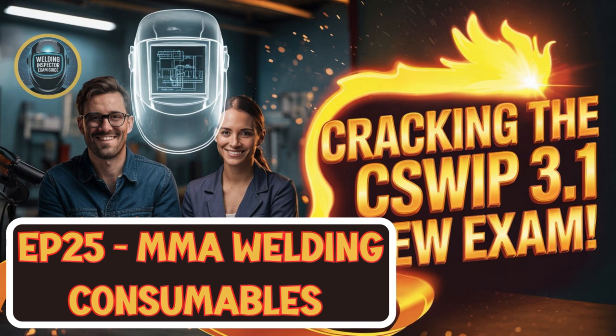Mm-hmm. And that slag does double duty. It forms a protective blanket over the cooling weld, helps control the cooling rate, and gives further protection from the air. But wait, there's more. This coating isn't just passive. It can actively add alloying elements into the weld pool. Really? Like what? Well, you might have silicon in there to deoxidize the weld, get rid of oxygen, or manganese, sometimes up to about 1.6%, which really bumps up the strength and toughness of the final weld metal.